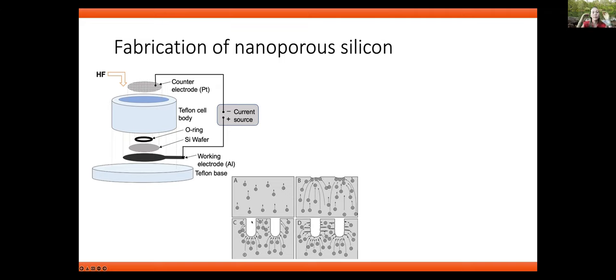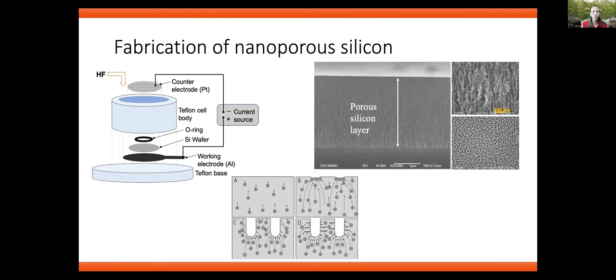We can also control whether the pores go only down or they also go to the sides and branch and become interconnected. So this is a well-controlled process, which allows us to produce nanoporous materials with highly controlled porosity and thicknesses. So here's an example of a porous silicon layer on top of silicon. This is air at the top. If we zoom in on the pores, we can see those highly interconnected pore network. And this is a top view showing quite small pores of roughly 10 to 50 nanometers in size.